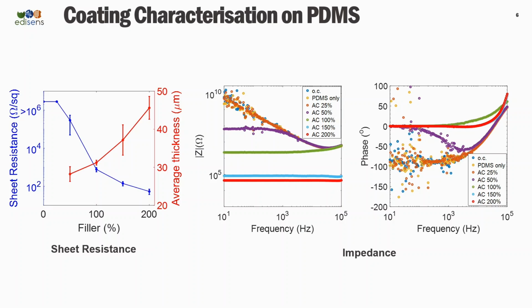for printed electronics. The impedance measurement just say the same thing. So low concentration of carbon is pretty much an open circuit, but then at some point you have percolation, and here, so for high concentration of carbon, the coating behaves like a normal resistor.